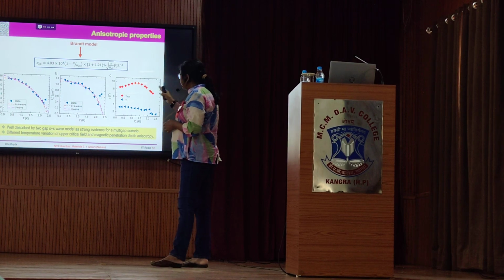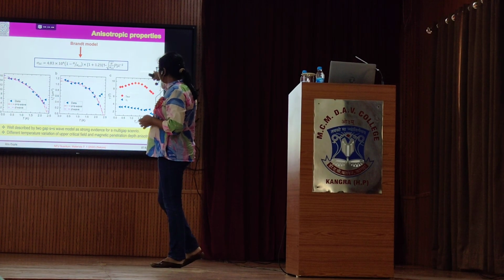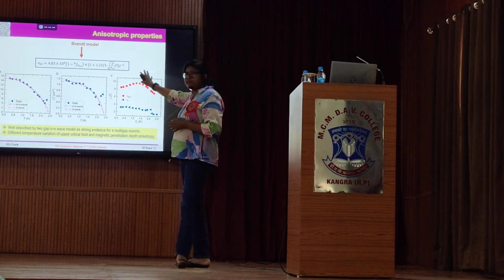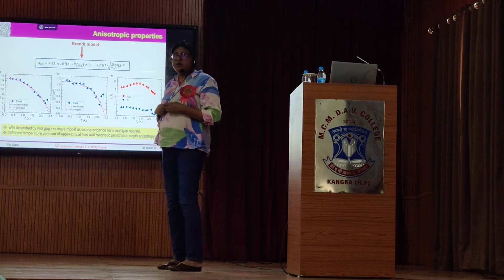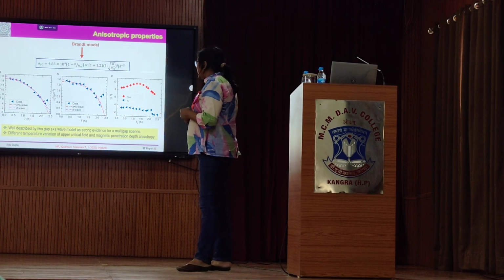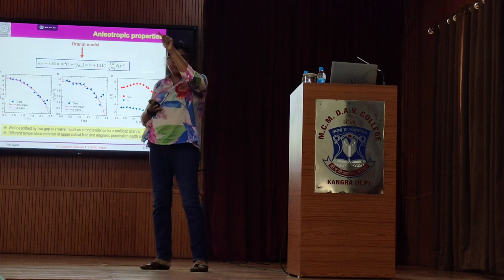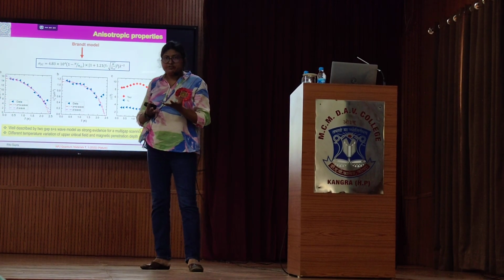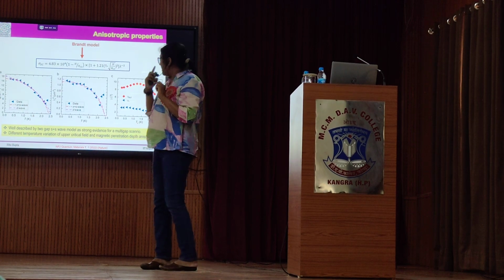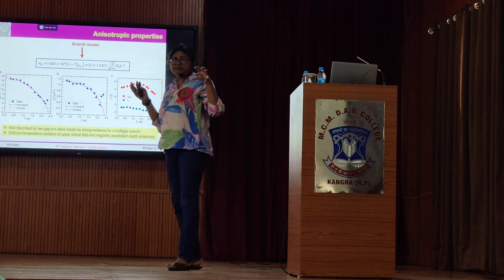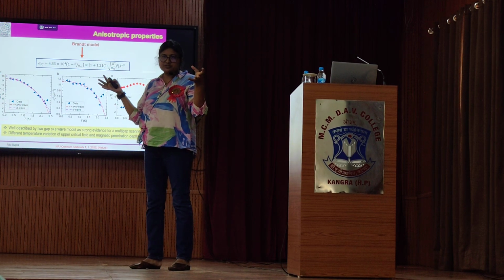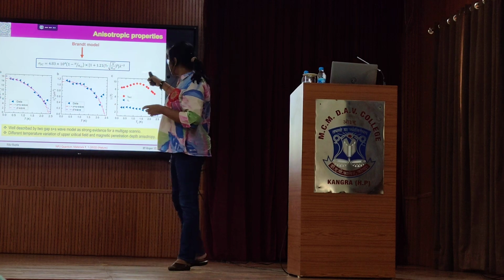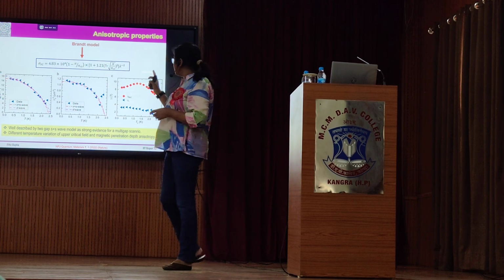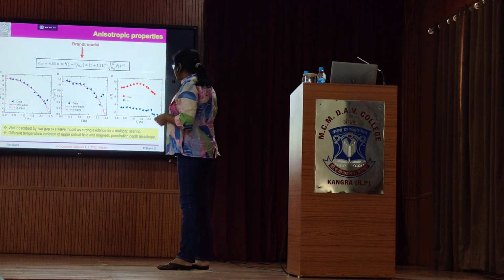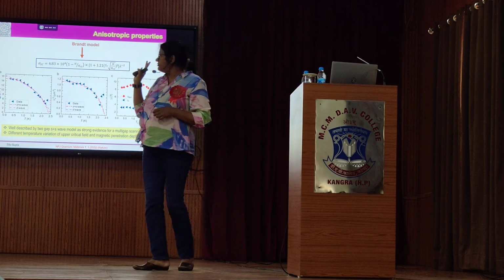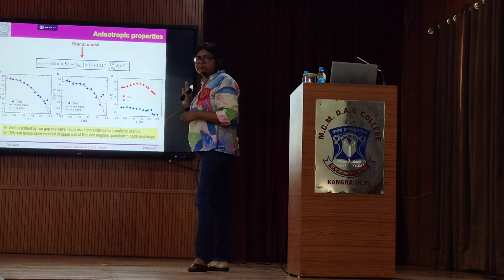Then we tried to calculate this inverse square magnetic penetration depth, and we fitted this data with different models for the gap symmetry. One of them was S-wave symmetry, where the gap is isotropic over the surface, or D-wave, where you have nodes at some points, and also you might have two gaps opening at different parts of the surface. That can also happen. Okay, so this is exactly what is happening here in this compound. You have a multi-gap scenario in this compound. This is what we estimated from the ambient pressure measurement.